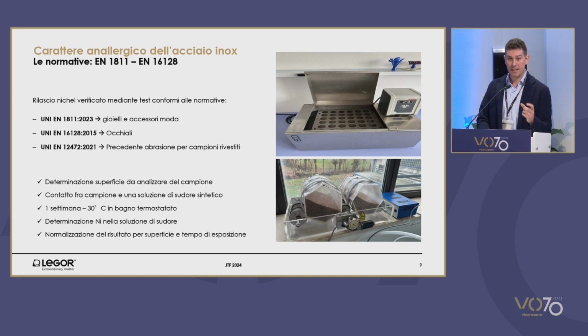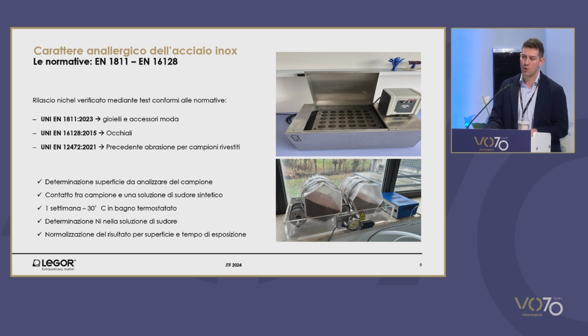And to measure the nickel release, artificial sweat is used on the surface. A test is performed between the object to be analyzed, the surface to be analyzed, and artificial sweat solution. With EN 1811, the object is totally included in the solution. In the case of eyewear, there's a band which contains artificial sweat, which is connected to the item of eyewear. The test lasts for a week. The temperature is some 30 degrees. At the end of the test, the nickel presence is detected.